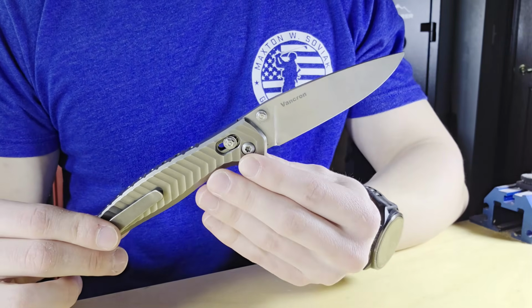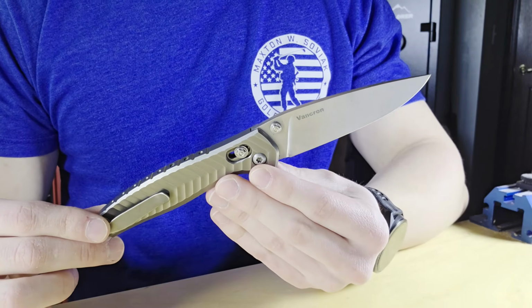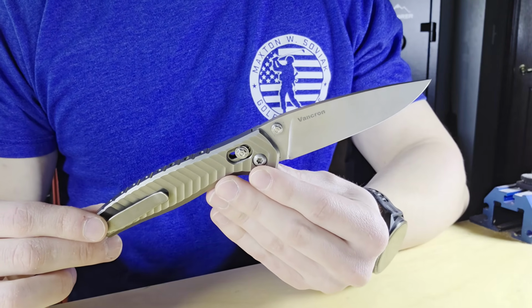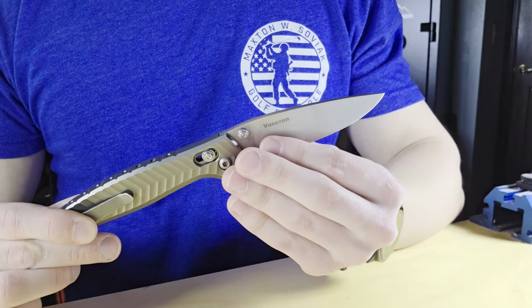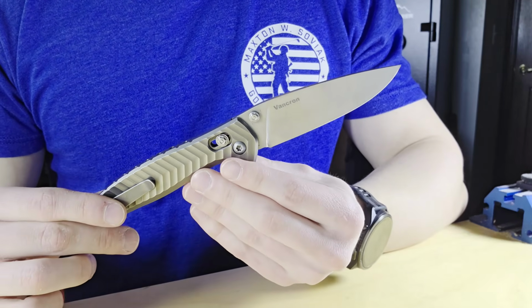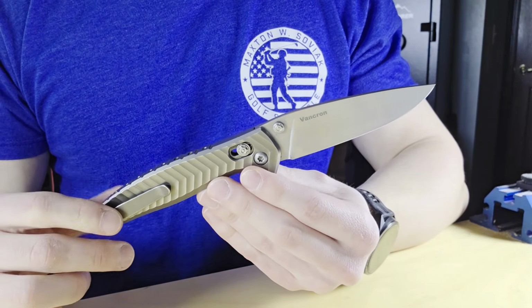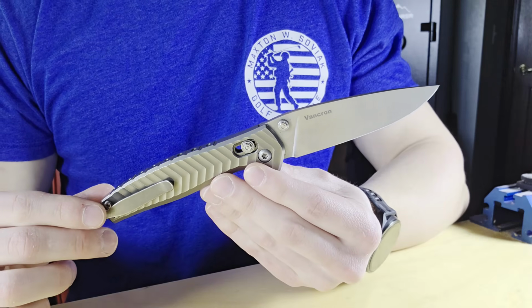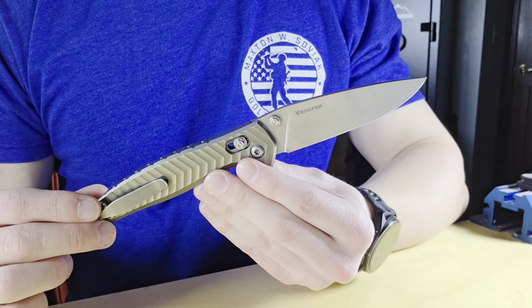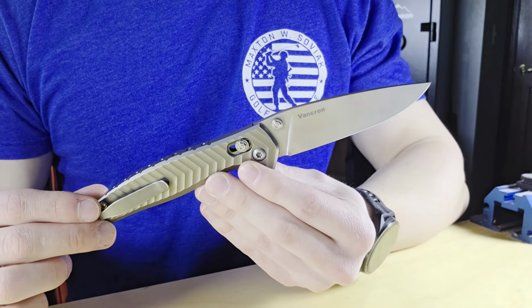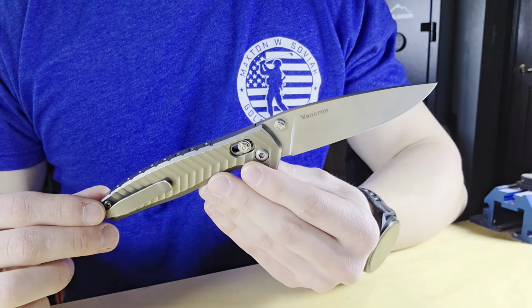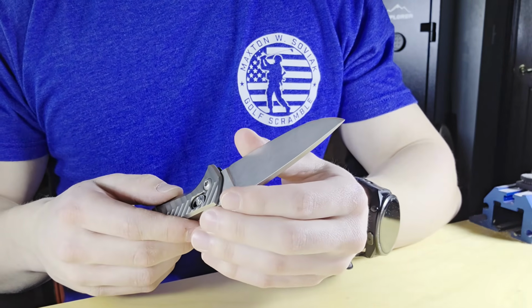The second sharpening I did on it was the exact same stone progression, followed by 1 micron, 0.5 micron, and 0.25 micron mono diamond emulsion by Stroppy Stuff on leather as well. This came up a little bit less aggressive after the strops, but it was still very sticky to the touch, and that tested at 126 BESS. And that's actually what this is at right now.